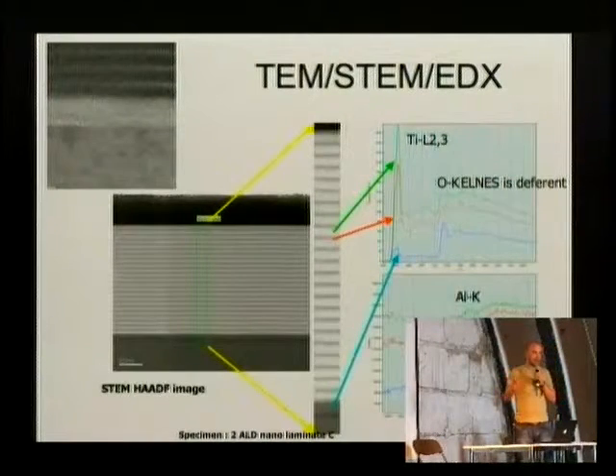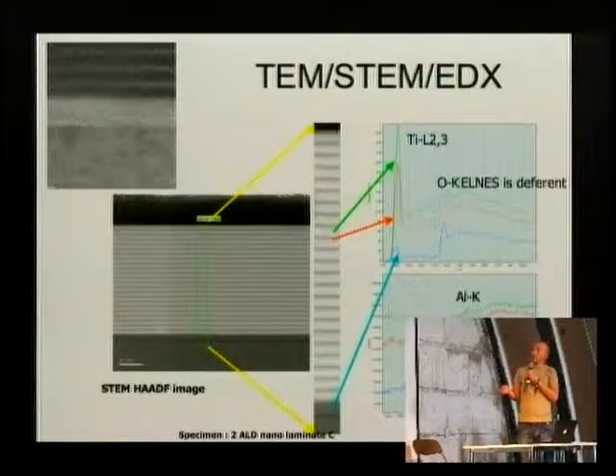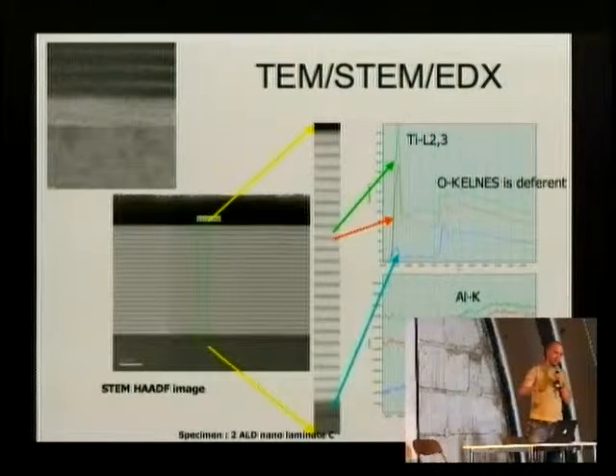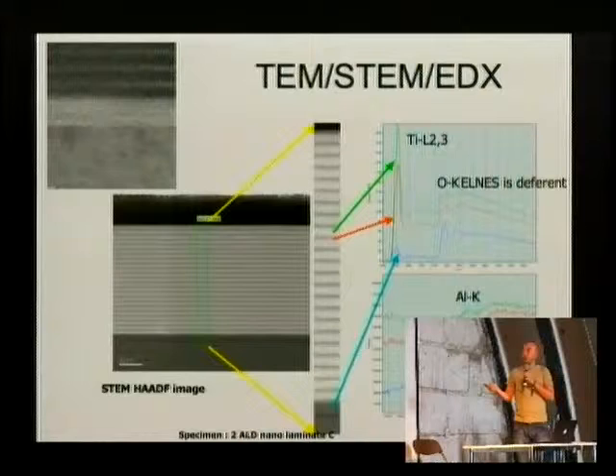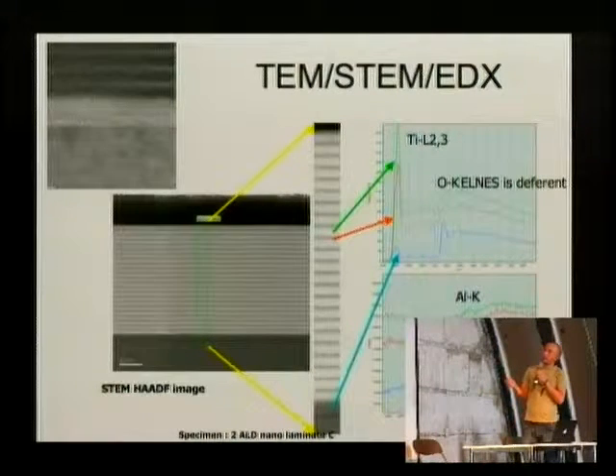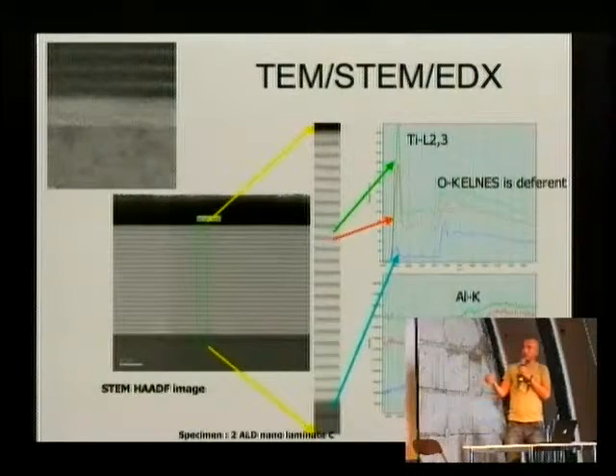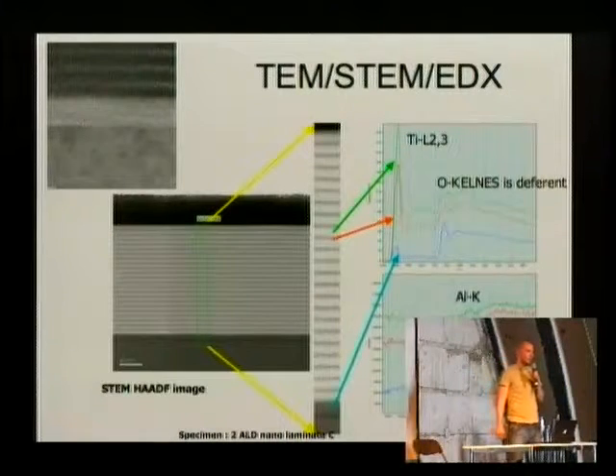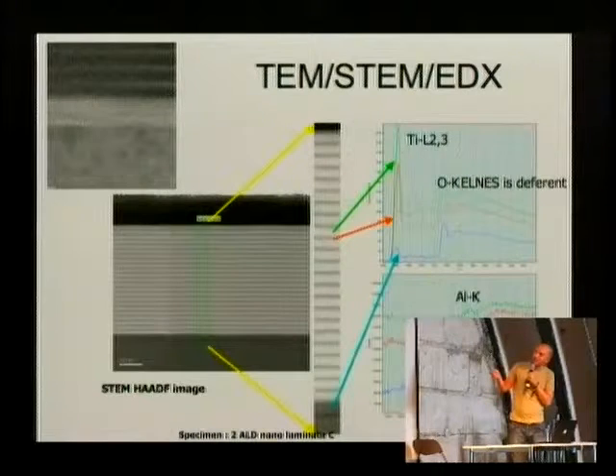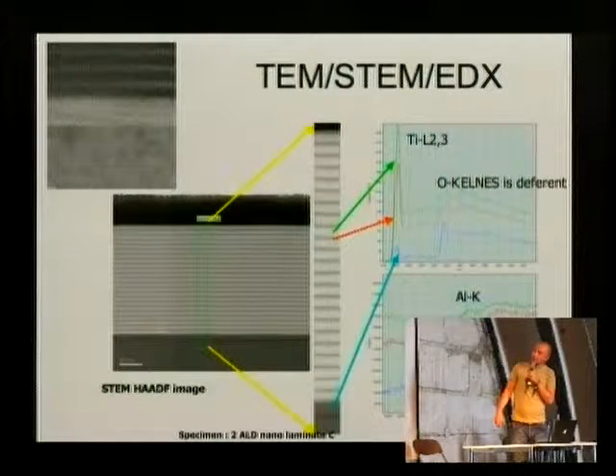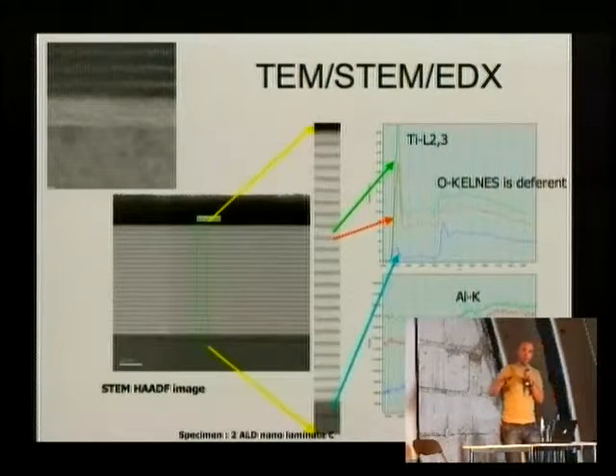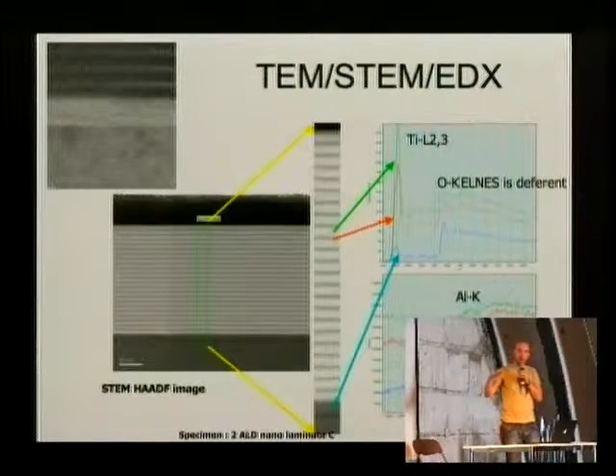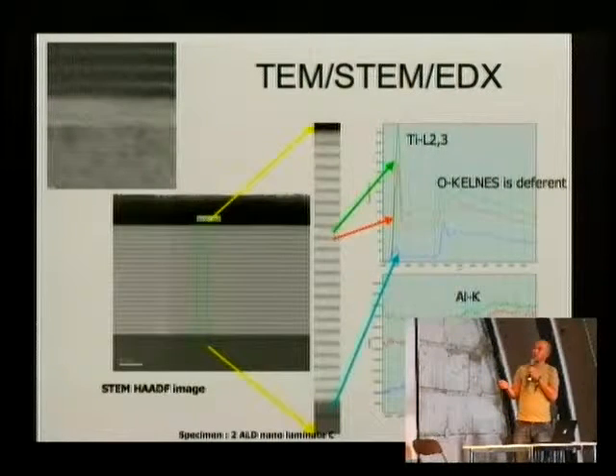So you prepare a lamella of the substrate in the same way I described. You put it into a transmission electron microscope or a scanning transmission electron microscope. One just looks through the whole substrate, the other one has also a scanning beam. The difference is not so big when it comes to resolution. Here you can see a picture that almost shows you atomic resolution. Unfortunately, it's a bit too bright in here, but maybe, I don't know. These little dots you see are not exactly the atoms, but this comes directly from the fringe or from the lattice pattern of the silicon.